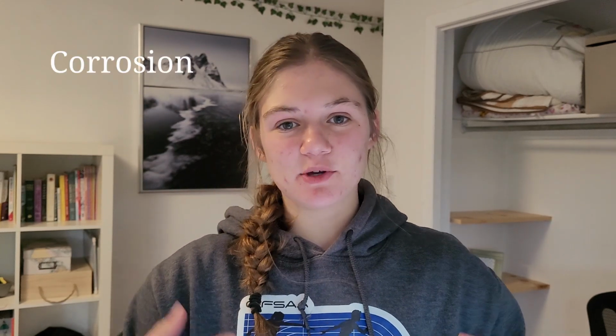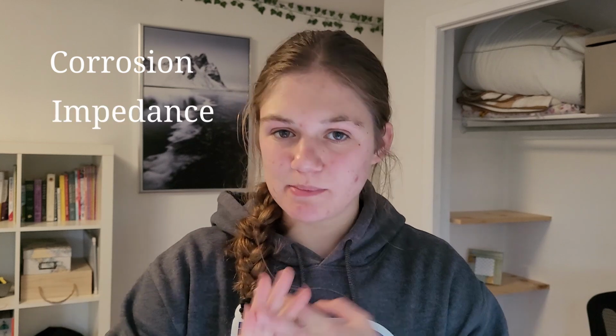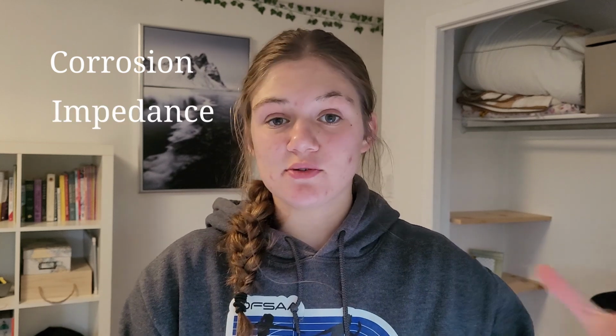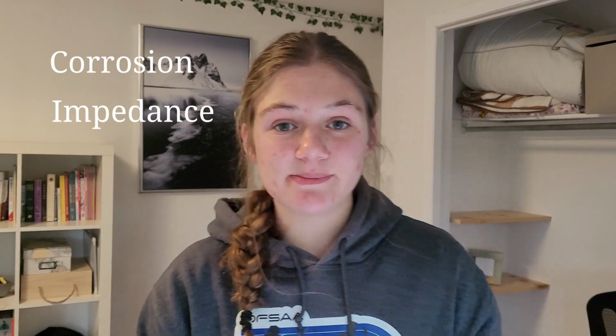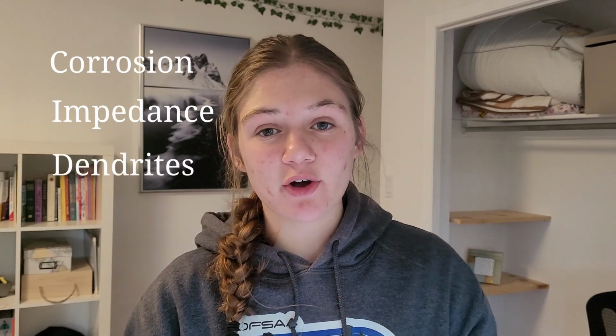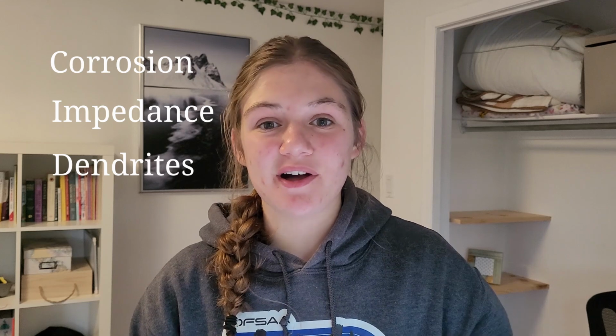As a TLDR, we broke it down into the 3 main aging mechanisms. First, corrosion, which is essentially summarized as unwanted chemical reactions. Then increased impedance, which is increased internal resistance. And the last one is dendrite formation, which is caused by uneven deposition of lithium. Those are, I think, the 3 main aging mechanisms that cause batteries to age a lot faster than they should, and result in us throwing away batteries sooner than we should and having more battery waste that causes all these terrible effects.